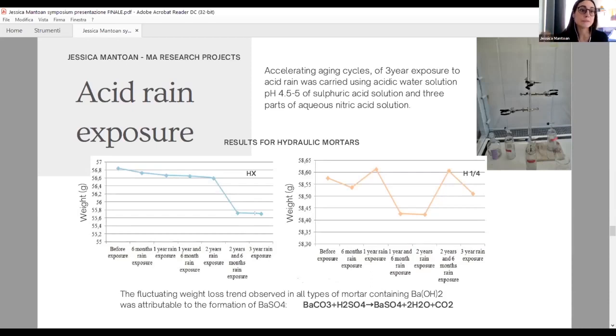That is because the acid solution is able to erode the lime binder of our mortar. Completely different is the result of our hydraulic sample containing barium hydroxide, because as we can see, the trend of the weight loss is going up and down. That is due to the formation of barium sulfate. Barium sulfate is the deterioration product of the reaction of barium carbonate with a sulfuric solution.